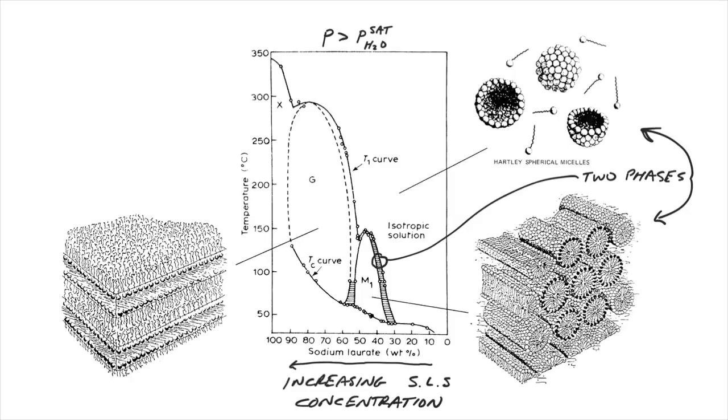The formation of such structures are often described in the literature as self-assembly, since the molecules themselves form these structures spontaneously. If non-ionic surfactant molecules and some water are dissolved in an organic solvent, a similar thing happens. The system self-assembles into reverse micelles, which have an aqueous interior and organic tails lining the outside, allowing them to dissolve in the organic solvent. If one then dissolves water-soluble precursors, such as inorganic metal ions, they concentrate in the interior aqueous parts of the reverse micelles, where they can form a nanoparticle.